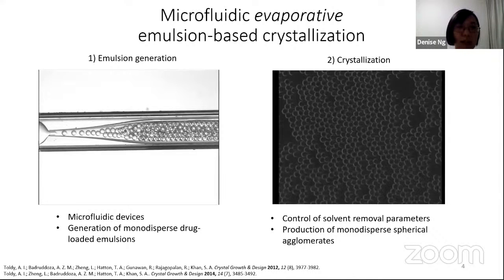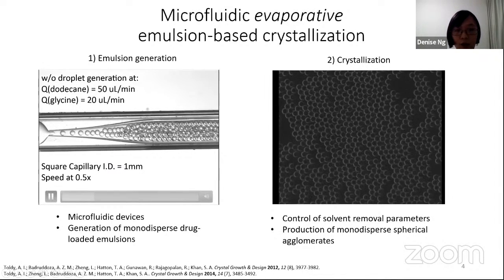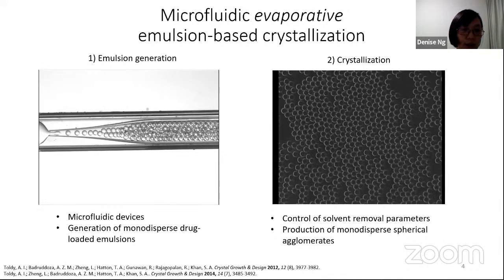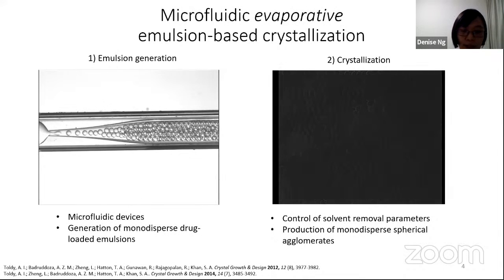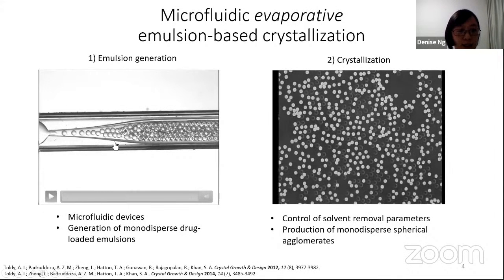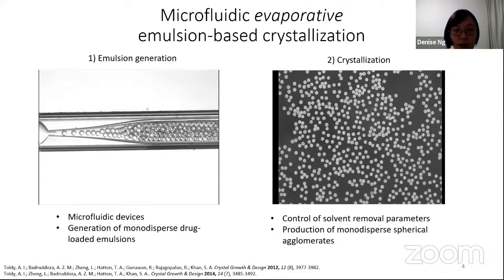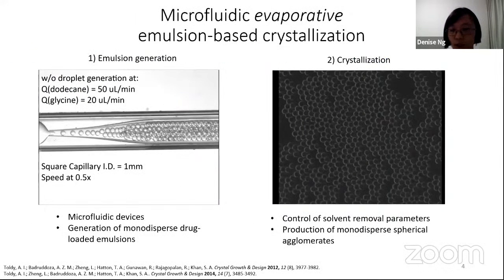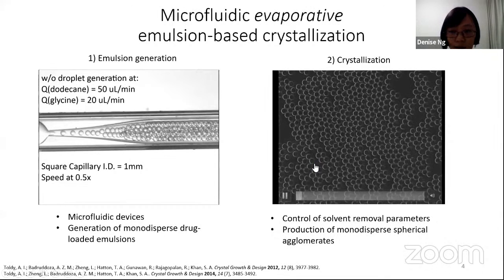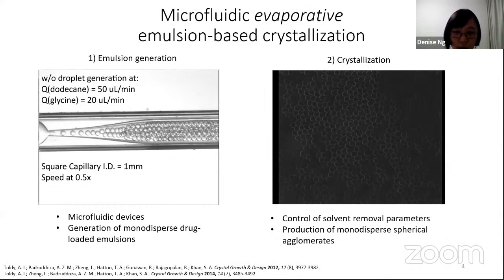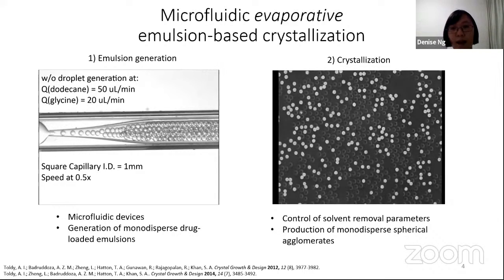It comprises 2 steps. The first step is emulsion generation. Here I have a model hydrophilic drug, glycine, which is dissolved in water. Then we emulsify it into mono-dispersed glycine-loaded emulsions, and this results in the dispensation of uniform contents into each droplet. Then we collect these emulsions into a thin film, and we can control the film thickness to control the solvent removal parameters. As the droplet undergoes evaporation, the droplet shrinks, and the drug within it begins to supersaturate and crystallize into mono-dispersed spherical agglomerates.